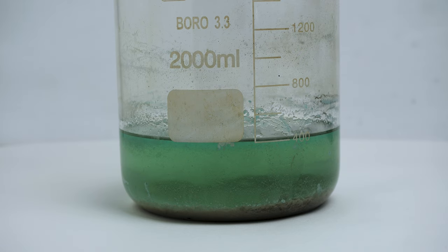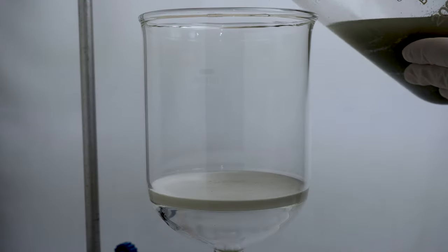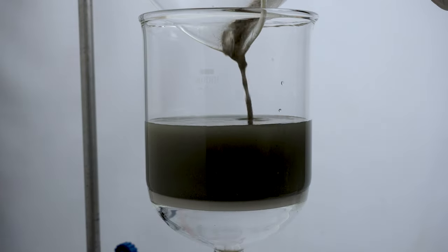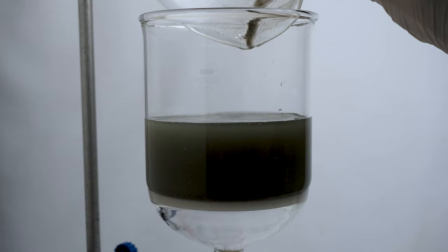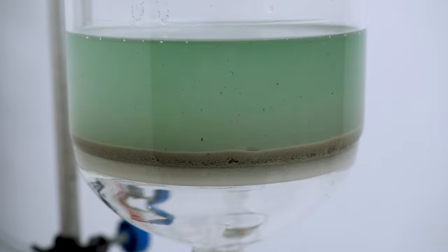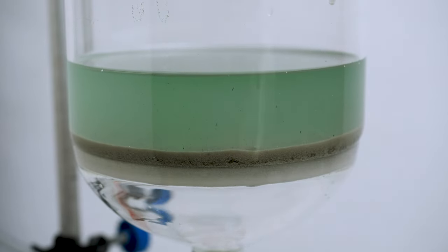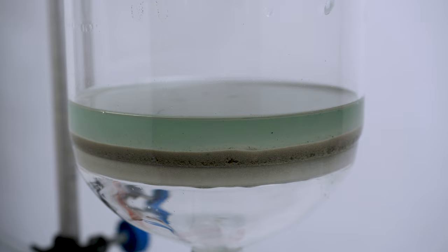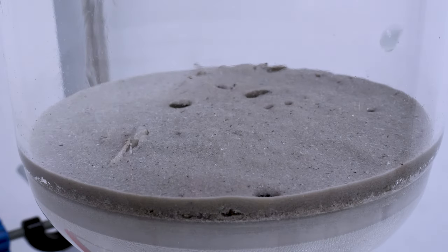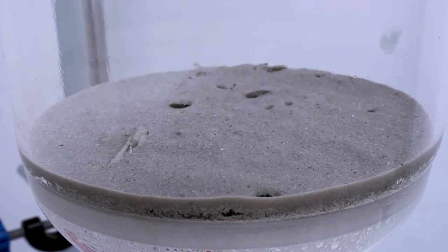This is after cooling in an ice bath for a few hours, and on to filtering. And here we have another surprise. In the previous boil, because my thermometer broke, I only guessed at the temperature. I must not have reached 200 C because we ended up with the monohydrate, which this is not. It's nice we get to see the difference though, because here we see that with enough heating, once the sulfuric acid is concentrated enough, it will completely dry the copper sulfate into the anhydrous compound. Because the product turned this white-gray color, we know that it's void of water. Fun to see the whole spectrum.